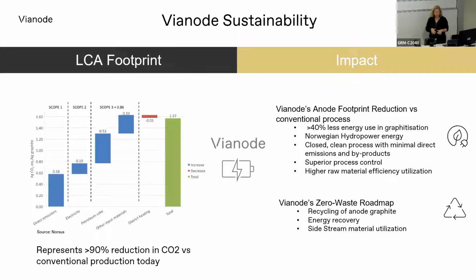What we see with our materials in our furnace is that we at Vianode have developed a furnace technology that is an entirely closed furnace, so that we don't have this kind of off-gassing in the area. By having this closed furnace, we are able to be much more energy efficient. So we use 40% less energy in the production of our material than you would in China. The other thing that we see is that because we are here in Norway, where we have access to green hydropower and power with a very low CO2 footprint, overall we are able to reduce the CO2 footprint of the graphite material that we make by 90% versus what you would see coming out of Asia. So it's a significantly greener material. It's what you want to have in your electric vehicle.